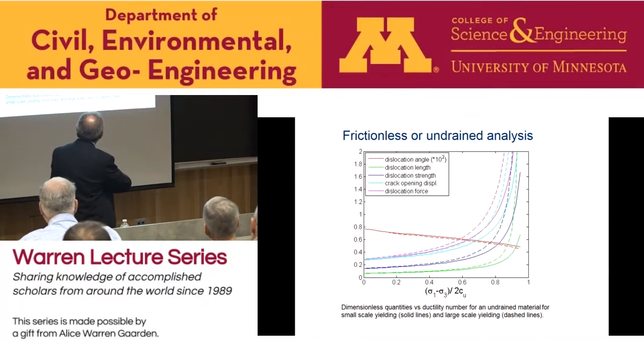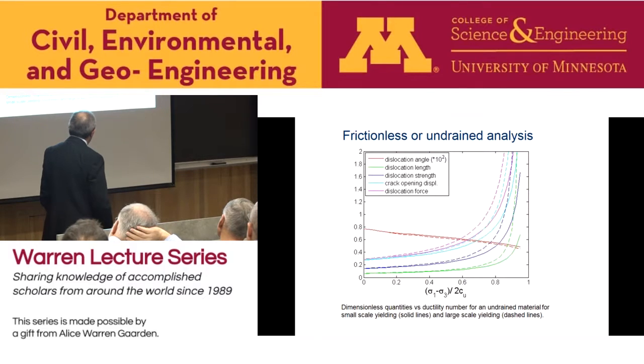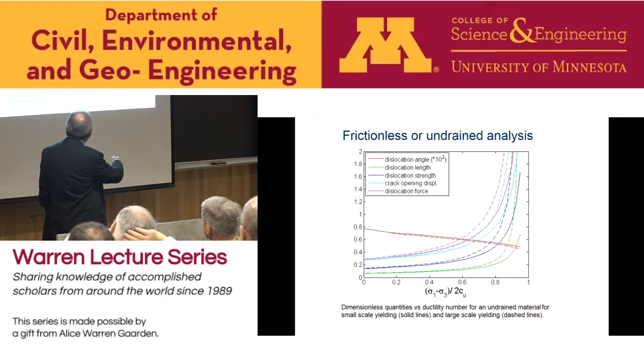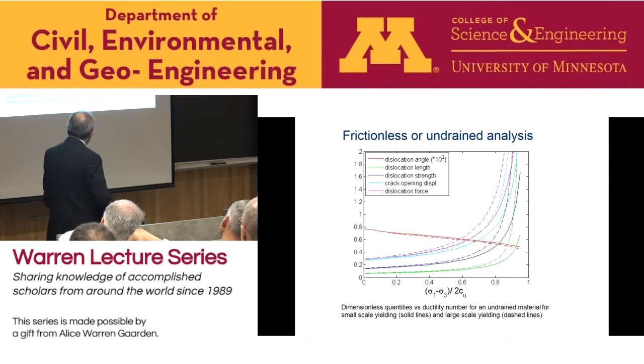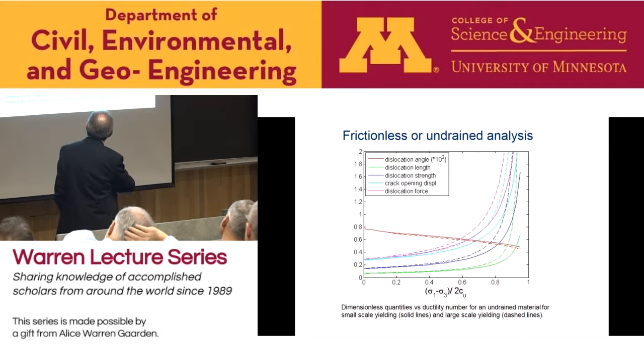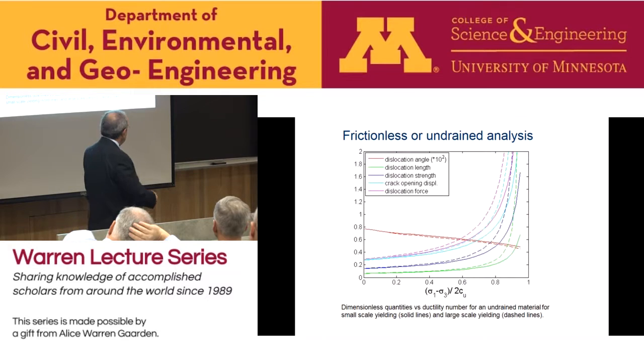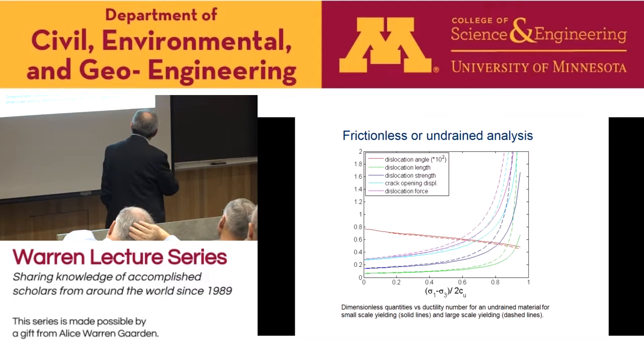And basically, if we look at frictionless or undrained analysis, friction 0, and we look at these unknowns I said before, the value of the unknown in dimensionless form is on the vertical axis as a function of the stress field. And you can see here that when we are in an isotropic stress field, it's easier to create and propagate a fracture. We need more energy if we look at the force, this blue line, for example, this peak line. We need much more energy to propagate the fracture as the field becomes non-isotropic, and beyond a certain value, it will not be possible to create a mode 1 fracture. And this is the solution for small scale yielding and large scale yielding.